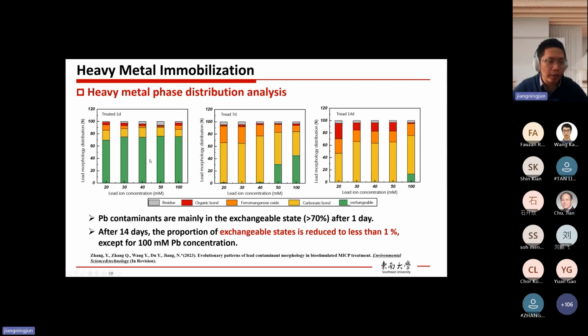So after 1 day of treatment, we can see that in all cases, most heavy metals are still in exchangeable state. It means that MICP has not yet worked quite effectively here. Then after 7 days of treatment, for low lead concentration cases, most heavy metal has been converted into carbonate bond. So it becomes more stable than the exchangeable case. For the 50 and 100 millimole cases, still a lot of lead is in the exchangeable state.